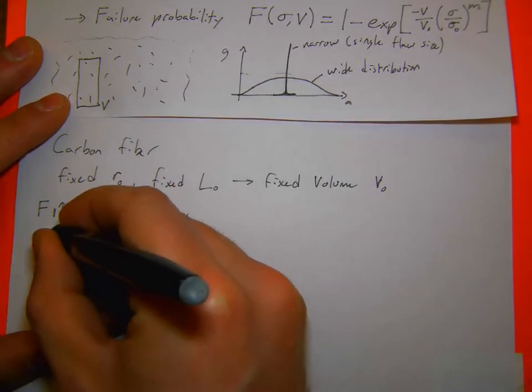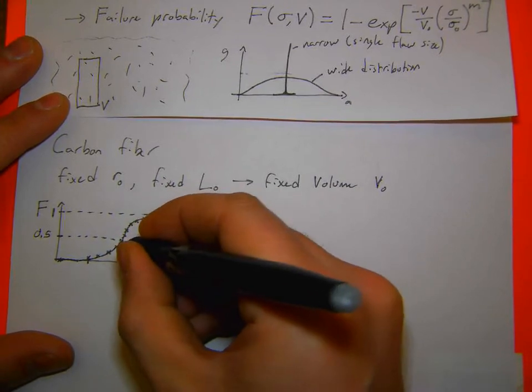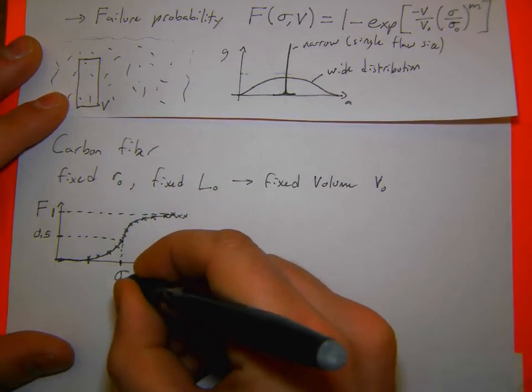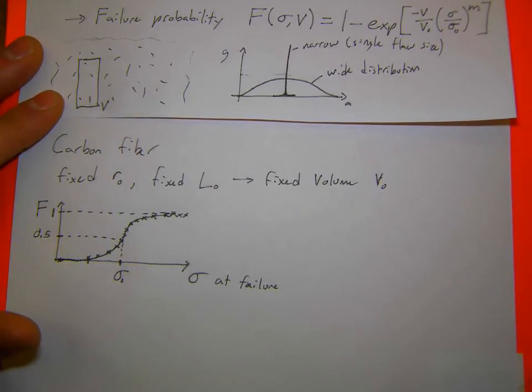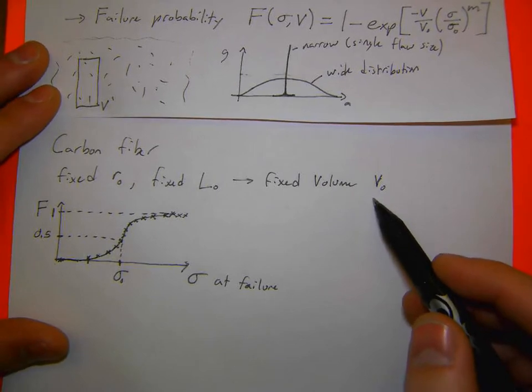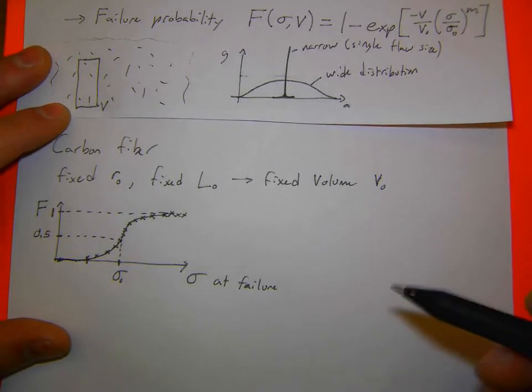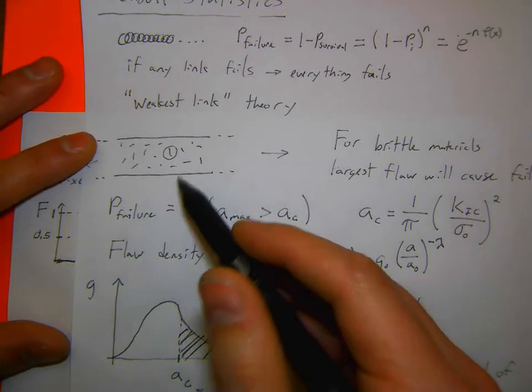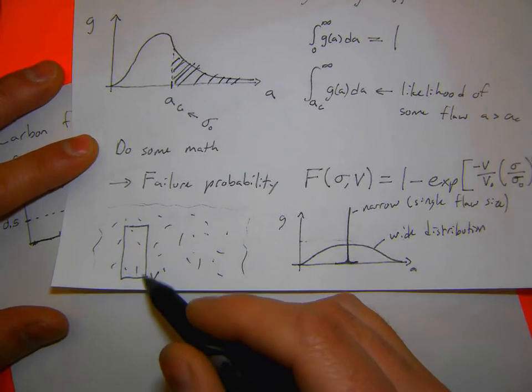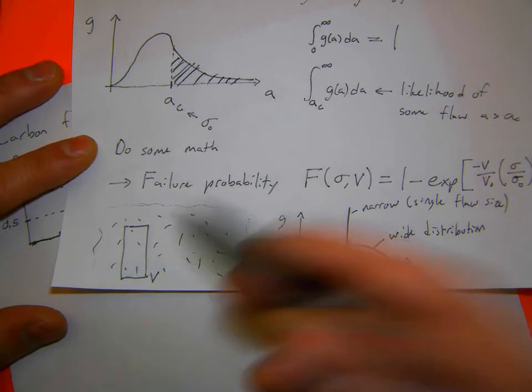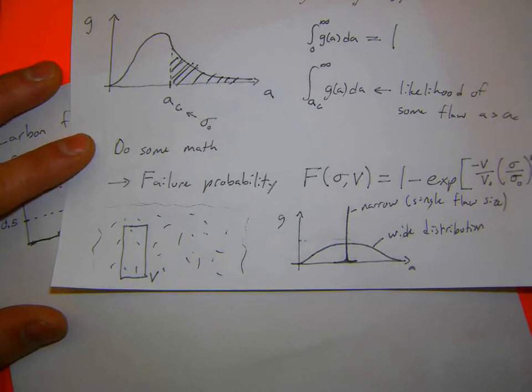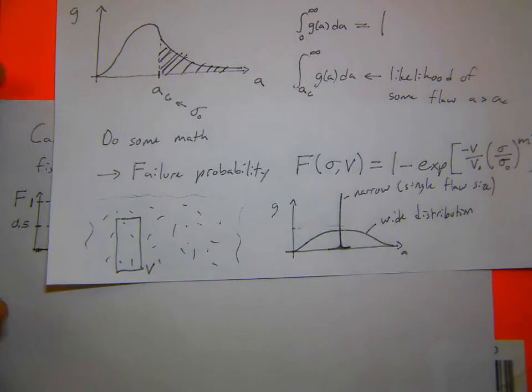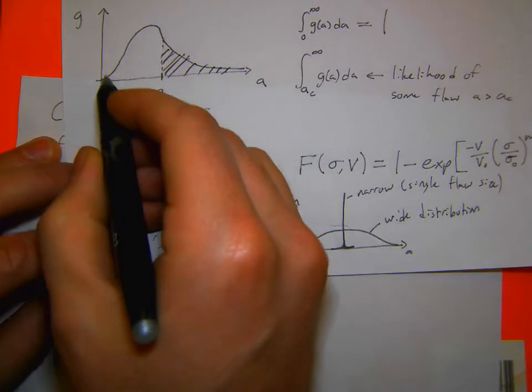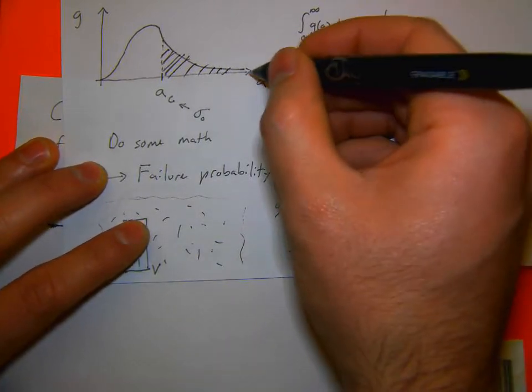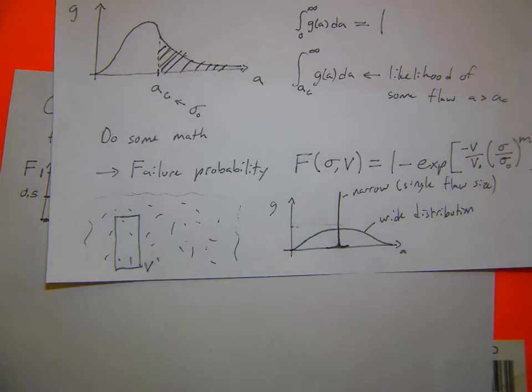But there's some intermediate stress where, say, half of them have failed. In our Weibull model, this is what we're going to call our reference stress, the stress at which half of the parts have failed for a fixed volume. The reason we want a fixed volume is the idea of a distribution of flaws. If I'm taking a bigger volume, I'm taking more of the sample, so I potentially have more flaws inside. Technically, this also means if I have an infinitely large part, I'm always going to get some very large flaw that's going to cause failure. So if I take a part that's 100 meters across.